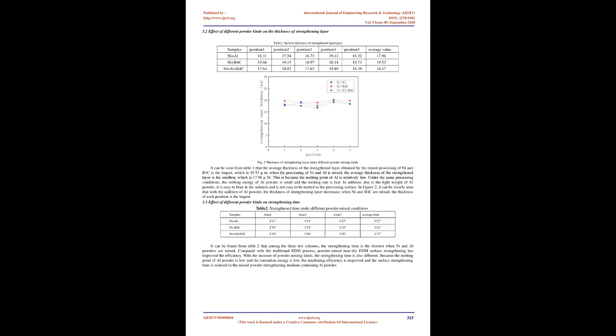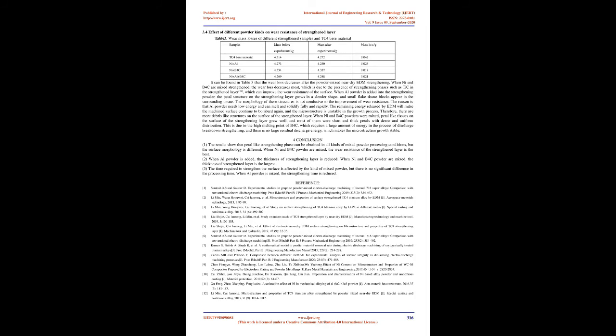Fig. 2 Thickness of strengthening layer under different powder mixing kinds. It can be seen from Table 1 that the average thickness of the strengthened layer obtained by the mixed processing of Ni and B4C is the largest, which is 19.53 μm. When the processing of Ni and Al is mixed, the average thickness of the strengthened layer is the smallest, which is 17.96 μm. This is because the melting point of Al is relatively low.